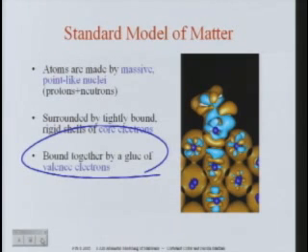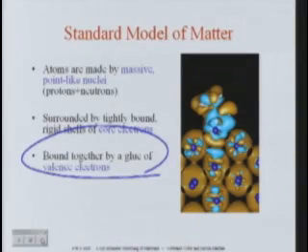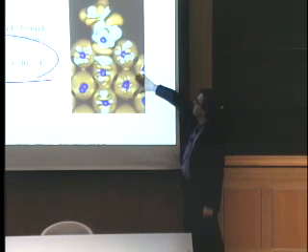And now you see, if you really want to recover some of the subtleties that are somehow invisible in this charge density picture, if you want to recover the tiny differences between the electronic levels, what you could do, and this is typical in electronic structure simulation, is take a charge density difference between a system in which you have a methane molecule attached to the platinum and one in which you don't have a methane molecule. And there, in this difference, you start seeing patterns of chemical bonding emerging.